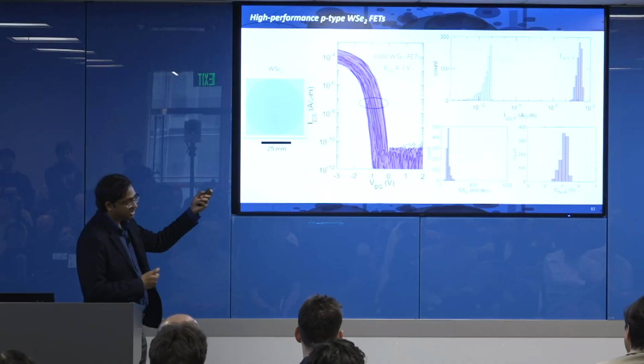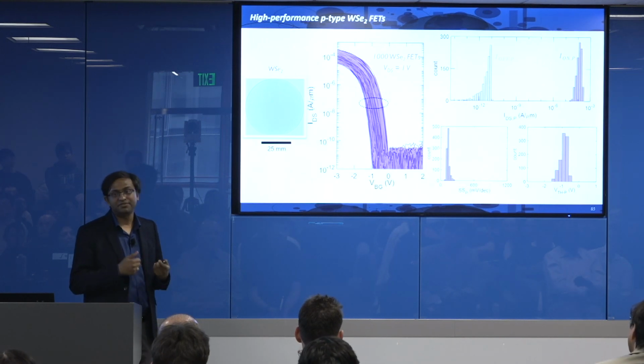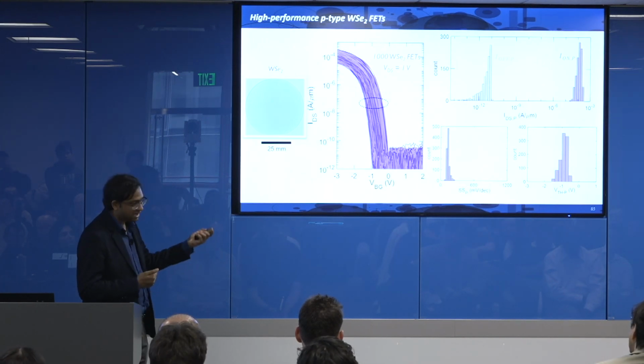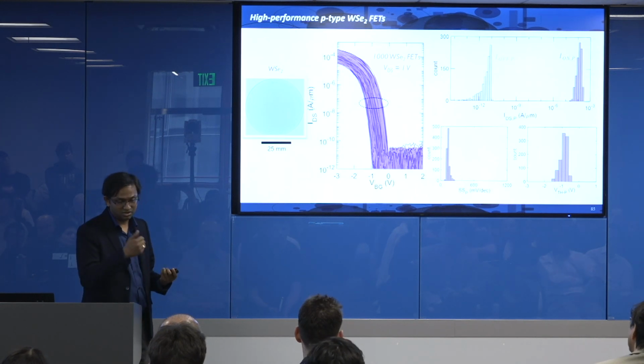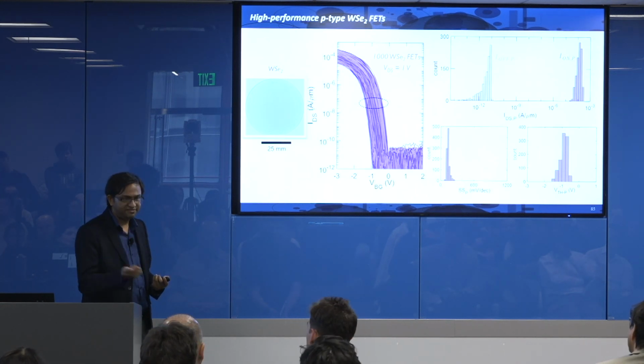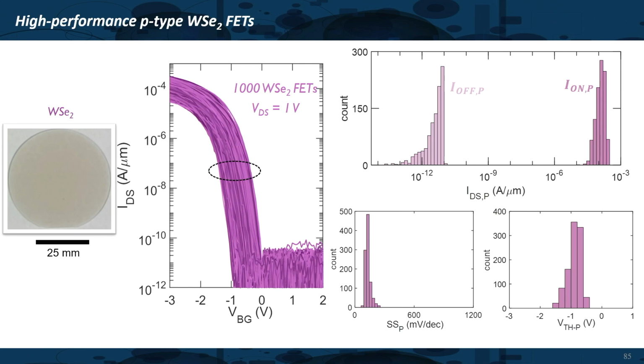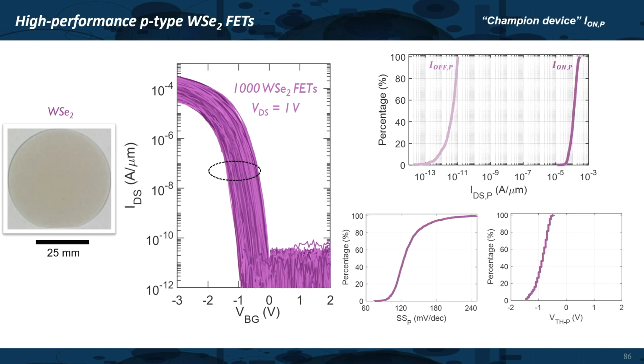So that is the NFET. Now what has been struggling in the community for quite a bit is the PFET, right? PFET performances have been even poorer. But we have now been able to achieve similar performing PFET. So our PFET currents are also now of the order of 250 to 300 microamps per micrometer, and we have been able to do that with something we are using called NO doping. So we have defect passivation, because defects were really creating a lot of problems with tungsten selenide. With NO doping, we are able to passivate these selenium vacancies, and we are able to get to very high performance. Device-to-device variation is also quite low.